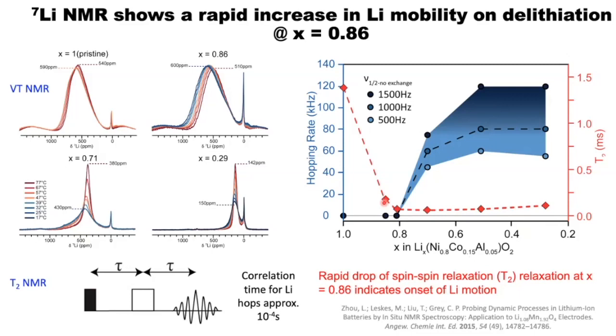So what Phil did was to go back and do the NMR, again of the pristine material, and then look at the partially delithiated materials. And again at about 0.86 lithium, he sees a noticeable change in the NMR patterns as a function of temperature. This is variable temperature NMR. By the time you're at 0.71, you get again this dramatic line narrowing, indicative of, again, lithium mobility.